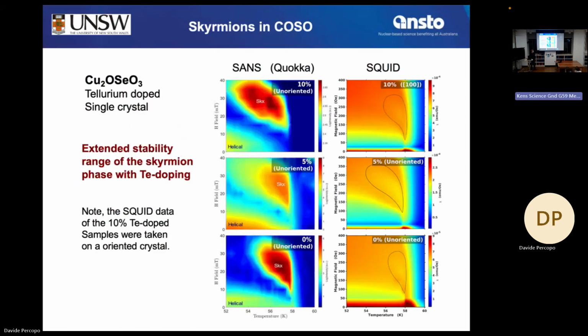Yes, indeed, here the neutron data. The skyrmion stability range increases, but unfortunately towards lower temperatures, not to higher temperatures. So we were hoping that we can shift it up, but well, at least it's a quite interesting result, and especially something for theoreticians to think about.